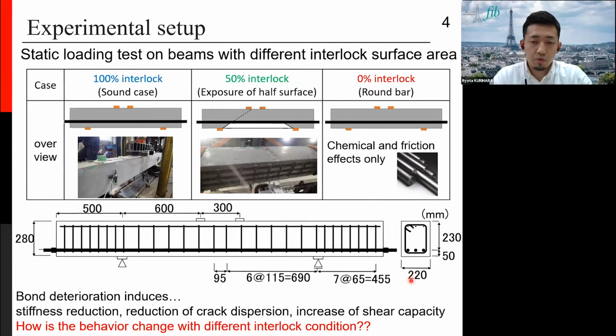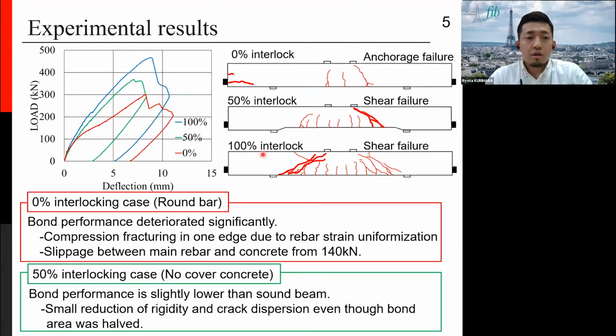In general, bond deterioration causes stiffness reduction, crack dispersion, or an increase of the shear capacity due to tie formation. Now, next is the experimental result. This graph shows the load deflection curve, and these figures show the crack patterns. The stiffness of the 0% case was greatly lower than the sound case after cracking, and more rigidity decline occurred due to slip between rebars and concrete from 140 kilonewtons.